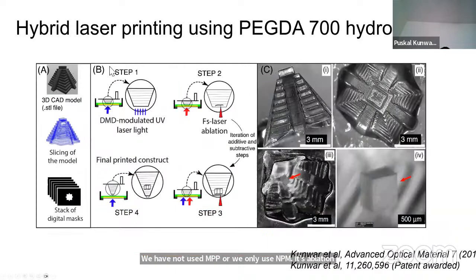Here is how it works: we have a CAD design, and that CAD design is sliced into a digital mask. Let's say our aim was to print a pyramid with an embedded cuboid structure. Then you print half of the pyramid using PSLM mode, then you bring in a femtosecond ablative step. You iterate these additive and subtractive steps, which is an automated process. At the end, after completion ablation, you complete the structure. So basically, this is the result.